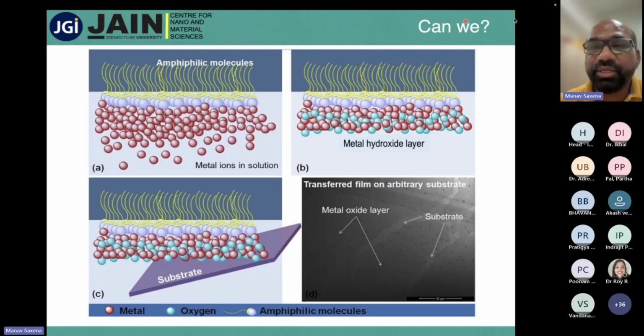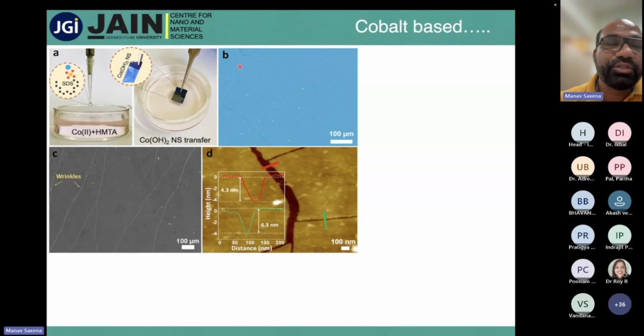So the question was, can we do this type of research? That is the hypothesis we asked ourselves, and then we made it. Now, for the cobalt based material, we started with cobalt ions and treated them with HMTA, hexamethylenetetramine. At 60 degrees centigrade, HMTA dissociates into ammonia and formaldehyde. Ammonia in the presence of water gives hydroxide ions and a basic medium. As SDS is on the top layer, the cobalt ion interacts with the SDS and the hydroxide generated from HMTA, and makes cobalt hydroxide.